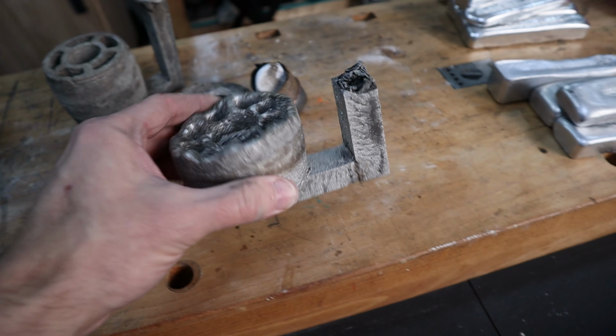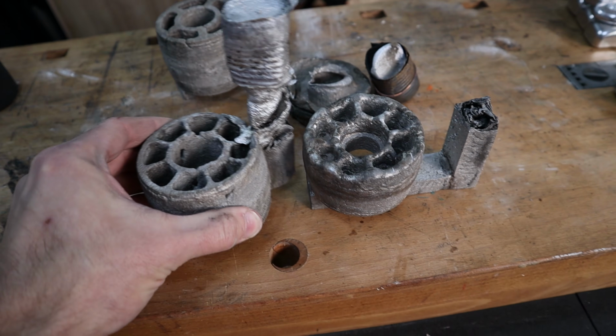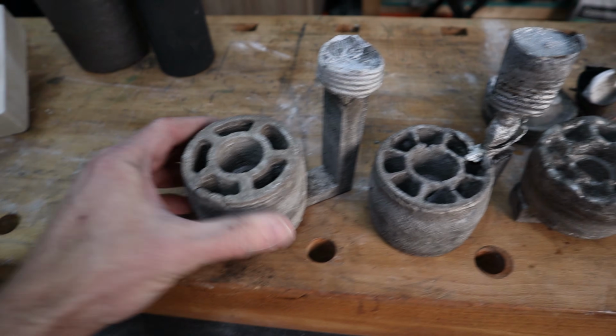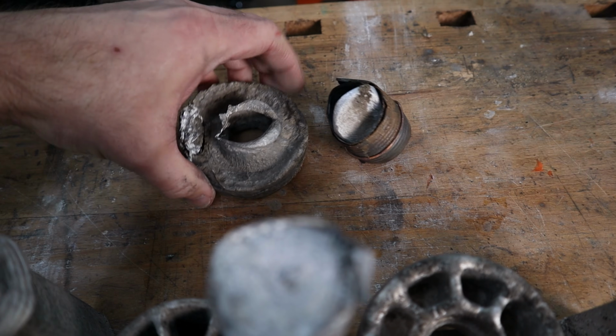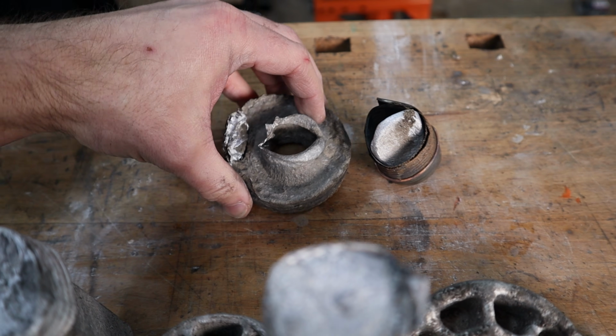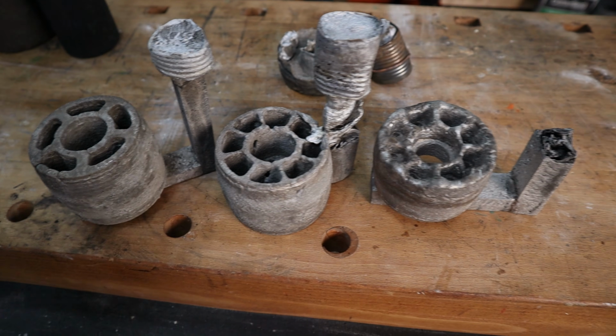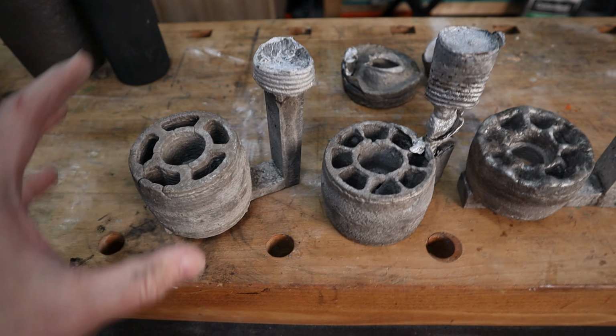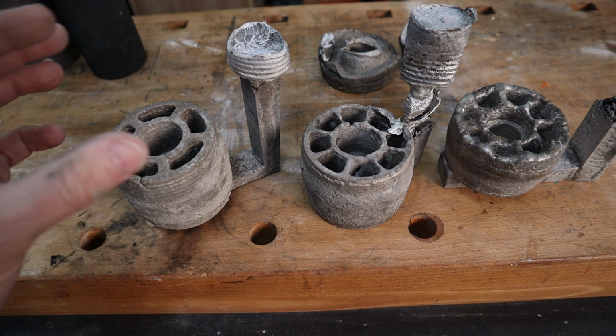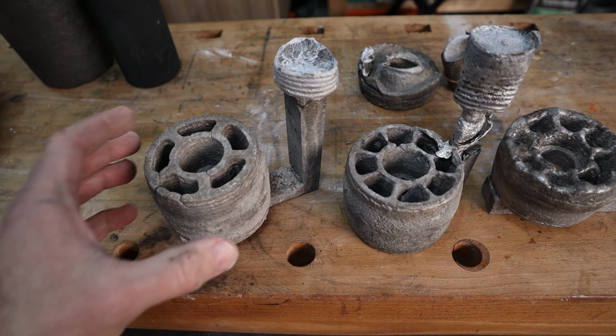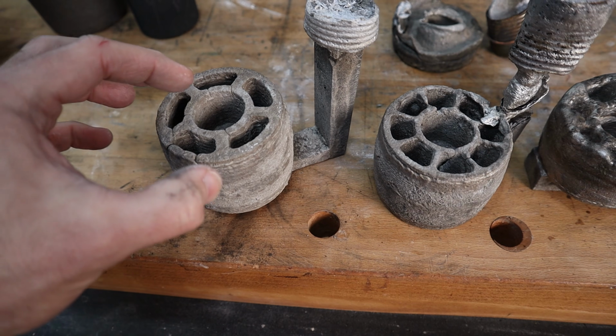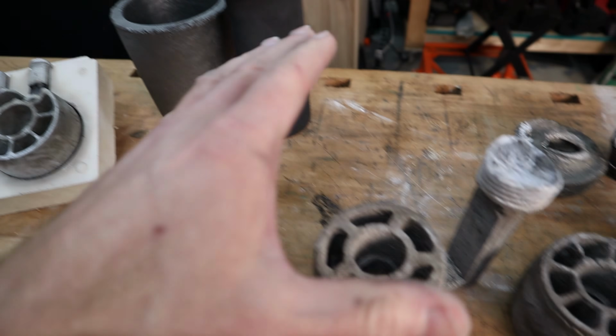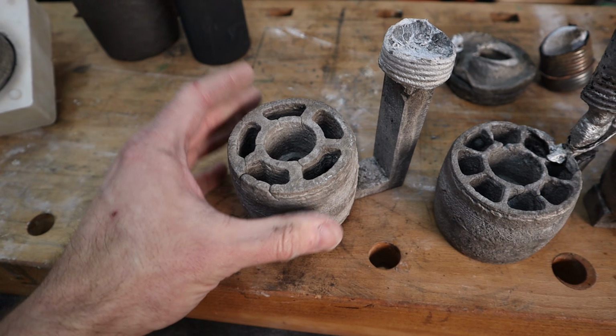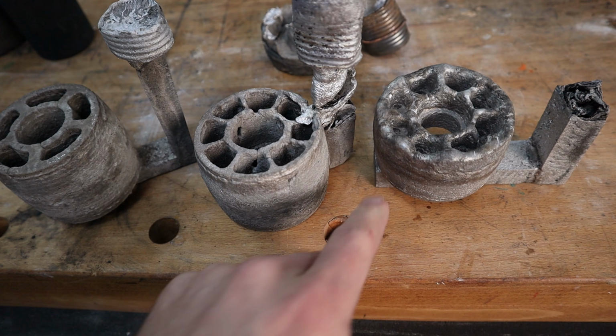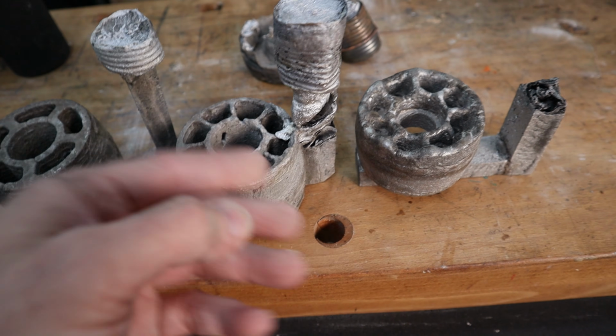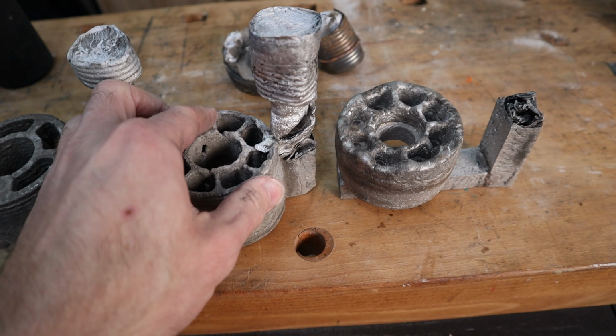So, lost foam, I had fail after fail after fail, after probably the worst fail. I was trying to pour this one late at night. I tried slightly different methods each time, and really it all came back to the fact that I'm trying to save material here. And I've got all these hollows in here because I don't have a crucible that's large enough to do a pour this big. So I adjusted the sprue, for example, coming down, because that was eating up some material. Well, that caused a problem.